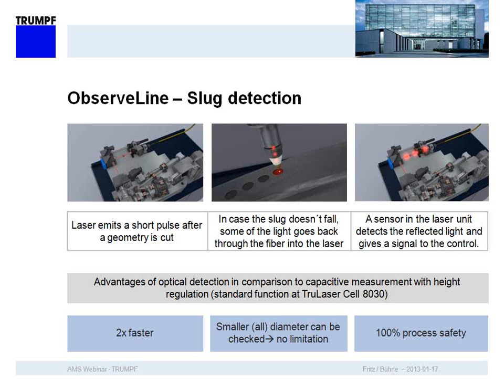But just in case a slug is getting stuck in a hole, which can always happen, then some of the light is being reflected through the fiber cable back to the resonator, where we have mounted a sensor that you see here indicated a little bit in blue. This sensor will give an error message or error signal, and the part can be treated accordingly and be taken out of the process. The same thing we can also do, of course, with our distance control, which is a capacitive sensing system. But it turned out that this optical system is way faster compared to capacitive fields, and it also can detect cutouts and holes which are much smaller. So we can achieve a very high process safety in this case.